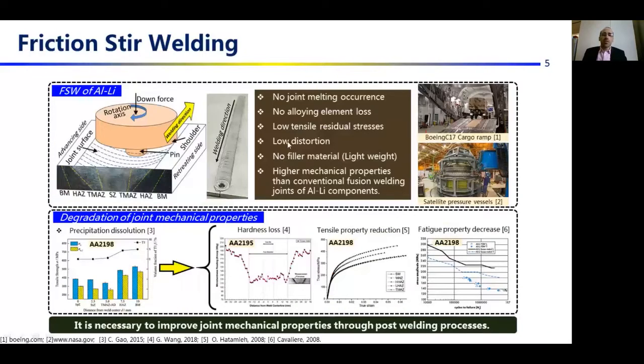Friction stir welding is a solid-state joining process that leads to no joint melting occurrence, no alloying element loss, low tensile residual stresses and distortion, and no filler material required, which leads to lightweight, and it leads to higher mechanical properties than conventional fusion welding for aluminum lithium alloys. It's been functionalized in the industry such as the airplane cargo ramps and satellite pressure vessels.